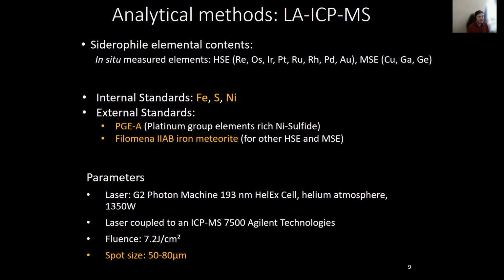So to do that, we did some in situ analysis using the LA-ICP-MS technique, and we analyzed highly siderophile elements and moderately siderophile elements using iron, sulfur, and nickel as internal standard, and two external standards, PGE-A and Filomena, which is an iron meteorite.